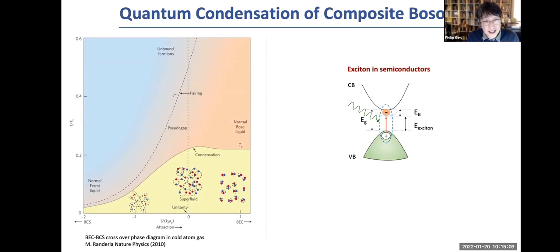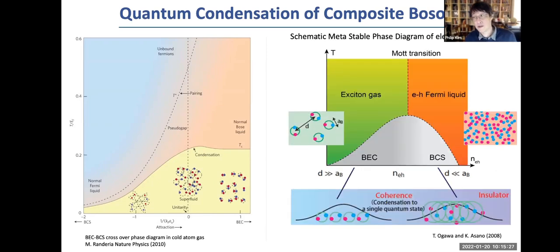But if you assume somehow this recombination process is rather slow, or even better, if you prohibit it, the exciton as a composite boson particle can condense into the exciton condensation, right? Theorists, in fact, have studied those kinds of limits. What if the exciton indeed lives long, and you have a controlled exciton density, such that compared with the size of the exciton, you control the distance between the excitons? You can get into the so-called BEC limit, where all these excitons are reasonably well isolated, and the excitons can condense into the so-called excitonic Bose-Einstein condensation. Often people call it the exciton condensation.